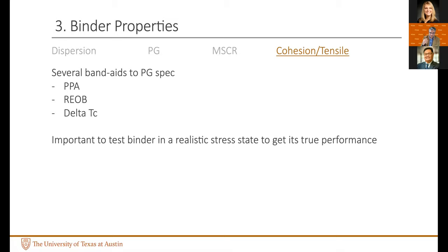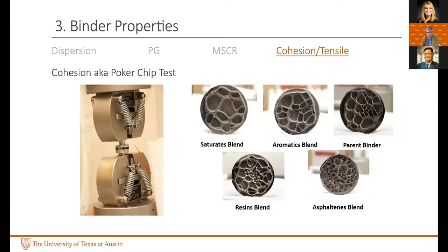We should not have to have a separate test every time there is a new additive or every time there's a new technology. If we are measuring binder performance with a true performance indicator, then it should be transparent to whatever is added to the formulation. And that was sort of the motivation where we went into this cohesion and tensile test, which is not an industry standard, but we developed it over the years as a binder test that tracks mixture properties that's easy to run in the lab. This was the original version of that test, a very small, we also call it the poker chip test because it's a very small thin film of the asphalt binder between rigid plates.